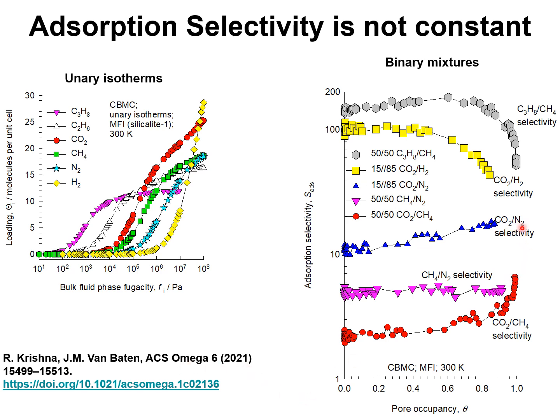Look at CO2 nitrogen. The difference in the saturation capacities is in favor of CO2 that has a higher saturation capacity, and therefore the vacant spaces in the pore topology at high occupancies is more easily filled up with CO2 that has a higher saturation capacity.